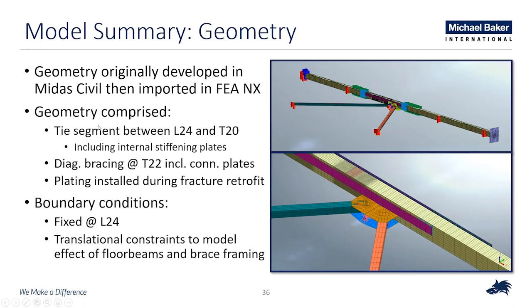So just a little bit of a summary of the geometry. As CY previously explained, the geometry was originally developed in MIDAS Civil and then was imported into FEA NX. After that, we extended the geometry of the local model to include the tie segment that is between the joints L24 and T20. L24 is the one that is at the middle support of the structure, and T20 is 4 panel points away. So that will leave the fracture that was at T22 approximately right in the middle of the model. We included also the diagonal bracing that was at T22, including the connection plates and any of the plating that was installed during the fracture retrofit, as you can see in the lower image.